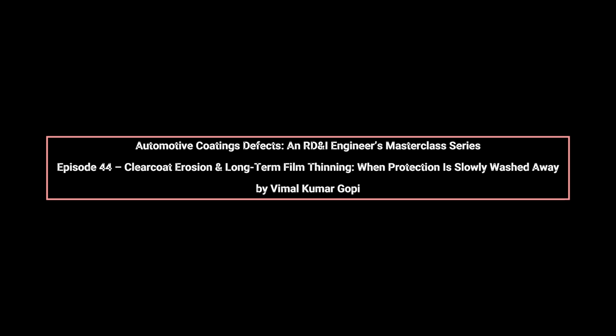From a diagnostic standpoint, clear coat erosion appears as uniform gloss loss, loss of color depth, increased surface roughness, and reduced resistance to staining. Paint thickness measurements reveal gradual reduction in clear coat thickness, particularly on horizontal surfaces and high wear areas such as door handles and roof edges.